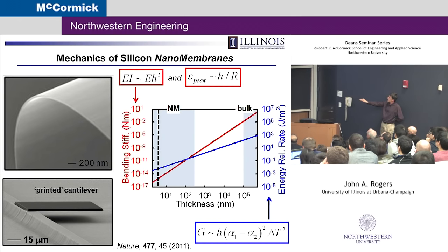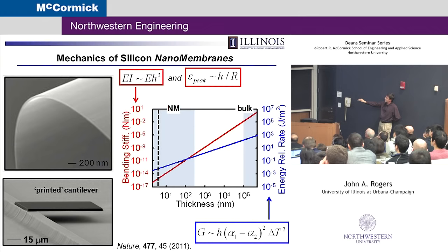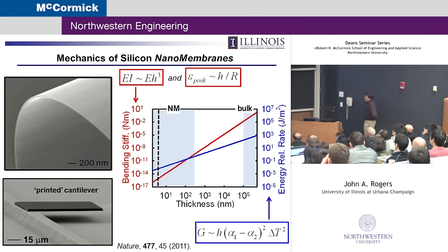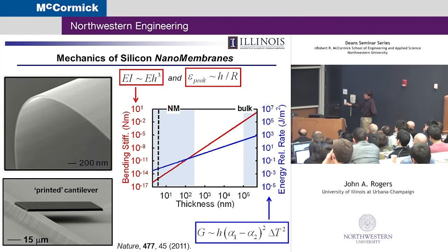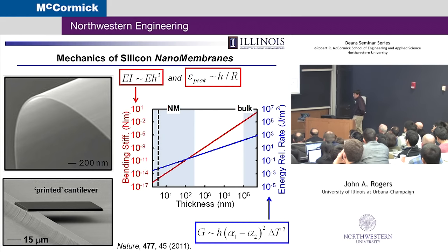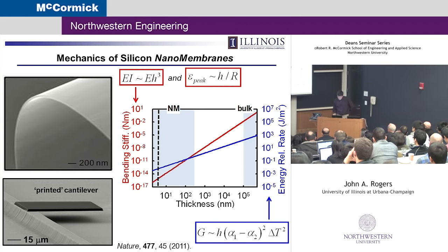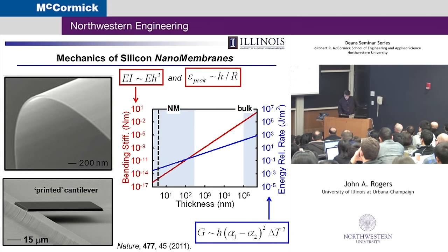You can see that over here. This is a plate of silicon. It's sitting in a cantilever geometry on a micromachined ridge on a plastic substrate. No adhesive at all right there. Just van der Waals forces can keep it suspended in that way, partly due to this linear downscaling of the energy release rate. So that's why we like silicon nanomembranes as a building block.